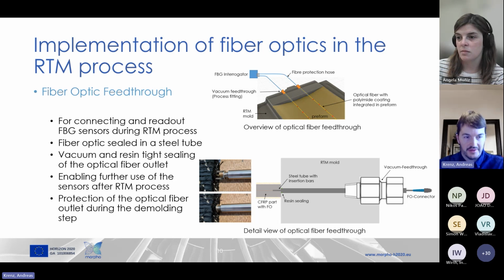which, again, the approach was to enable the connection of the optical fibers during the RTM process. So, it was realized as follows. I switch on my laser pointer. We have two through holes in the RTM mold where this feed-through solution is positioned. And we used a steel tube where the optical fibers are fed through and inner sealed with a vacuum-proof sealing. And next to this inner sealing, we had this outer sealing of this steel tube using this process fitting with the inner vacuum sealing by tightening with this process fitting.